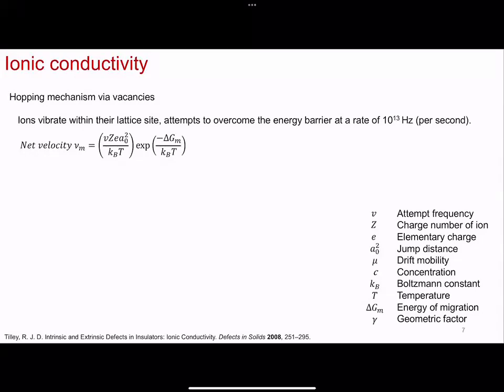So, you know, in lithium iron phosphate, right, it's a 1D tunnel structure. So if it's going along the fast ion transport direction, the 010 direction, that jump distance of 3 angstrom is going to be different than jumping in between the channels, which is farther, like 4.5, 5.5 angstrom, right? Depending on which site you land up. So now the crystal structure comes into play, and k_B T is the Boltzmann constant times the temperature that you're at. Okay, so what we've done so far is we're just saying this ion can diffuse if it can overcome some delta G, and it can jump that site, or the distance a naught.